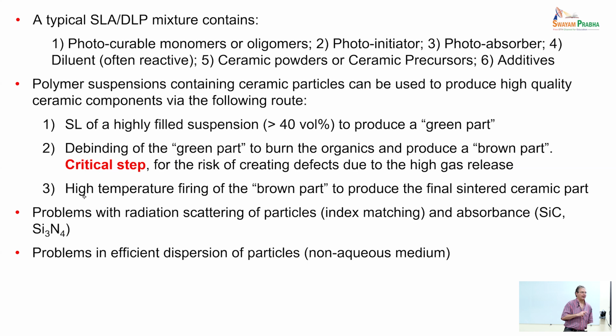The final issue that you have with this type of approach, photopolymerization, is that you have to disperse your ceramic particles into your liquid polymer. And people that make ceramics know that you can generate a lot of slurries quite efficiently, but typically they use water-based slurries. And there are a number of ways in which you can avoid agglomeration and precipitation of the powders. So you can stabilize ceramic powders quite effectively in water, chemically, or using steric interactions between the particles.